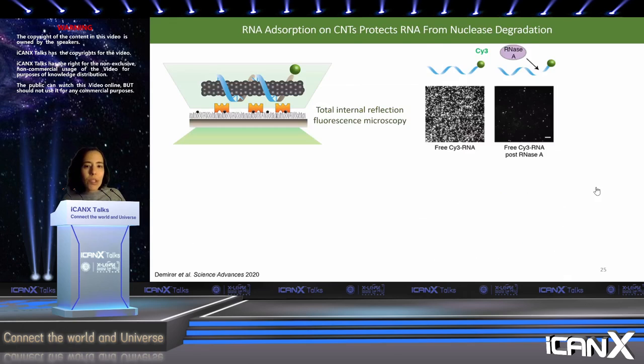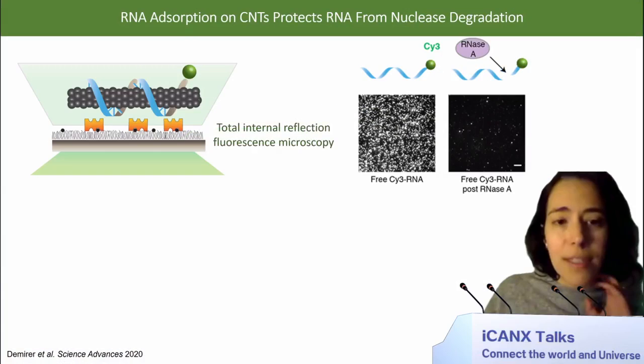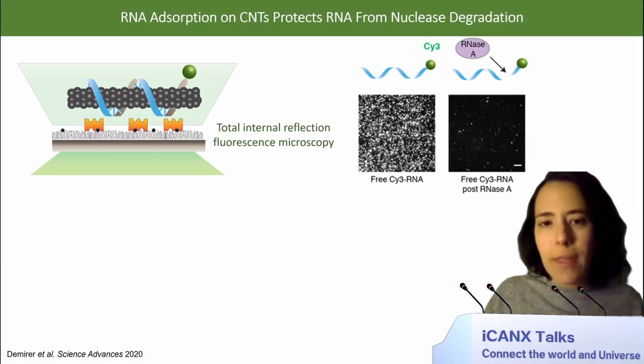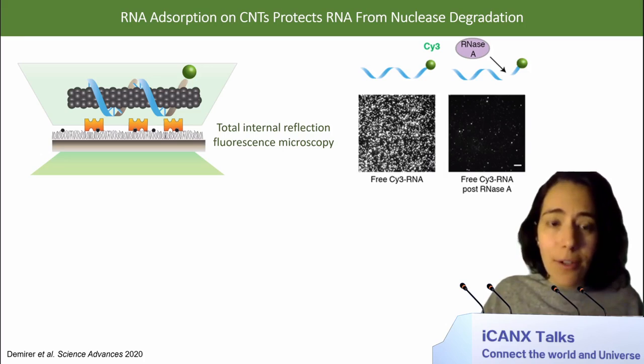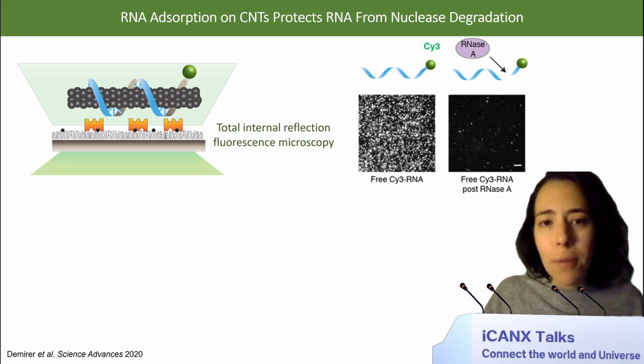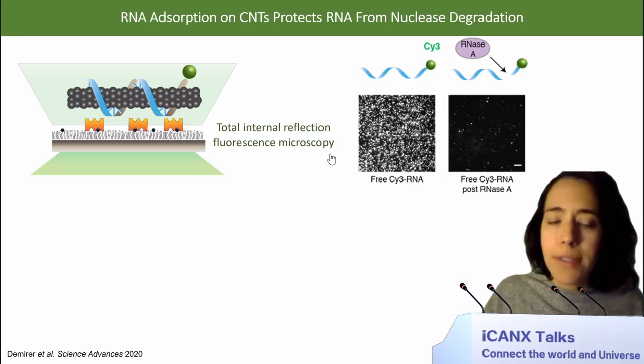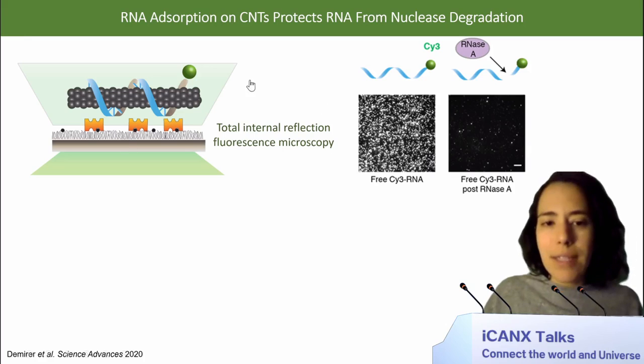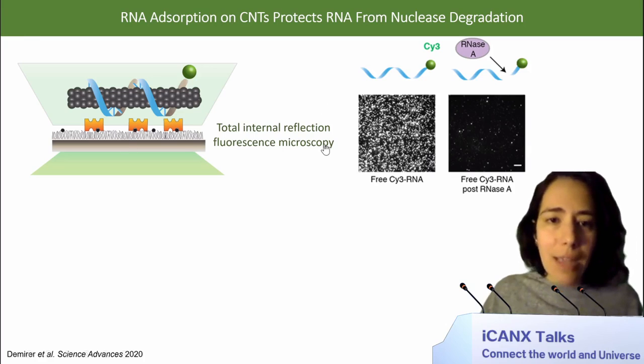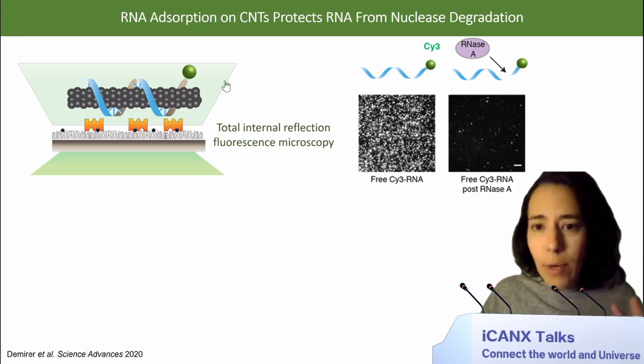Now, in addition to enabling RNA to go inside the cell, another potential mechanism that allows high efficiency could be the protection of these cargoes from degradation. So in the case of DNA, but especially in the case of RNA, these are polymers that are highly susceptible to endonuclease degradation. And so what we did is we performed a single molecule total internal reflection fluorescence microscopy assay. And this is a technique that allows us to assay the integrity of DNA or RNA polymers on a single molecule level. The assay works something like this.